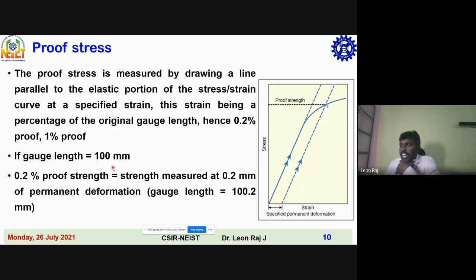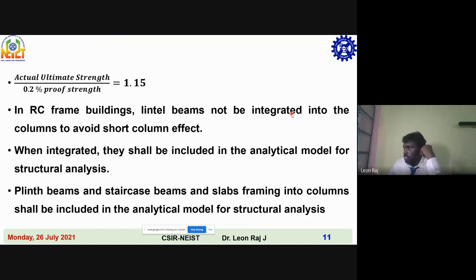So I want to give an example. If you are testing a specimen and our gauge length is 100 mm, then the 0.2% proof strength is equal to the strength measured at 0.2 mm of permanent deformation. Your gauge length at that point shall be 100.2 mm. So at that point, you can get this point. From this point, if you draw this same slope, you will get this proof strength. Then the ratio of actual ultimate strength to 0.2% proof strength is equal to 1.15.